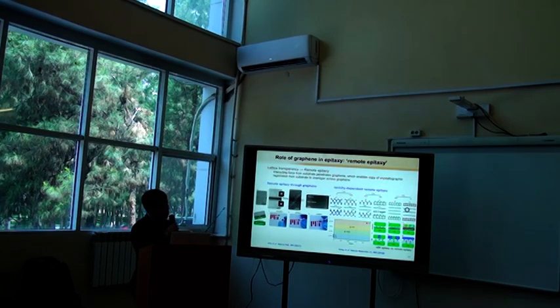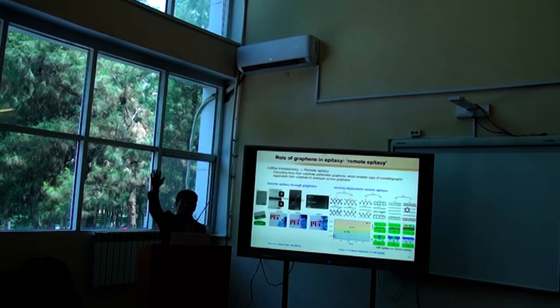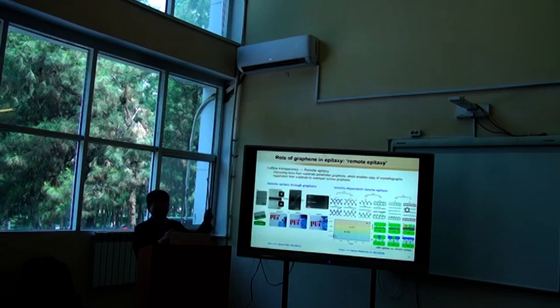And now you can see the interacting force. There is a substrate and the graphene layer, and the overlayer goes on the substrate. Here the interacting force from the substrate penetrates the graphene layers, which enables the copying of the crystalline arrangement of the substrate to the overlayer, grown through the graphene layers, which is remote epitaxy.